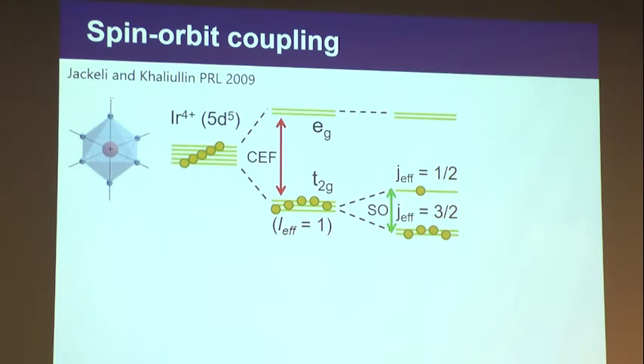Take a material like iridium. If you put iridium in an oxygen octahedral environment, the crystal field splitting from this cubic crystal field is so large that you're essentially removing the eg electron states, and you're left with basically a 3-level t2g system with 5 electrons. Starting with that, if your next highest energy scale is spin-orbit coupling, then the end result is that you are left with a singly occupied effective J = 1/2 state and an effective J = 3/2 state, which is all filled. This effective J = 1/2 state is a strongly spin and orbital entangled state, because it's not just spin up or spin down. The wave function looks like this, with 3 orbitals all mixed in with the 2 spins. So that's the peculiar thing about materials with a strong spin-orbit coupling.